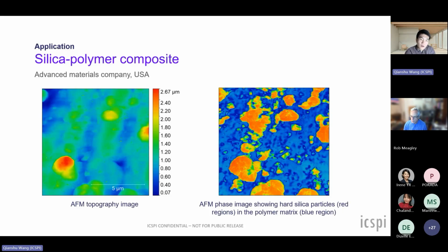hardness of materials. On the right-hand side, you'll see that the hard silica particles, which may be hard to see in the topographical image, show up much more clearly now as the dark red areas compared to the blue polymer matrix area. This can be very useful for people that are building composite materials, that are trying to mix two materials together. They have an idea of what the proportions of each material are relative to each other going in. They want to get an idea of how well these materials are distributed. They want to get an idea of what kind of structures are coming out. Are my final resulting distributions what I'm looking for?